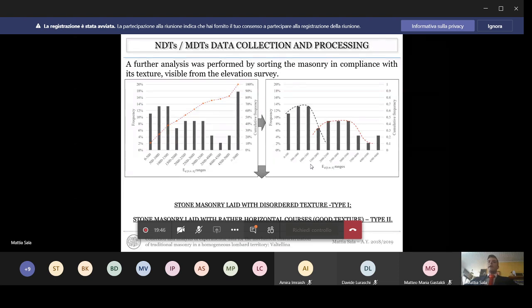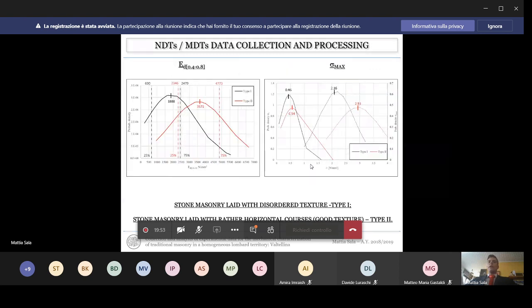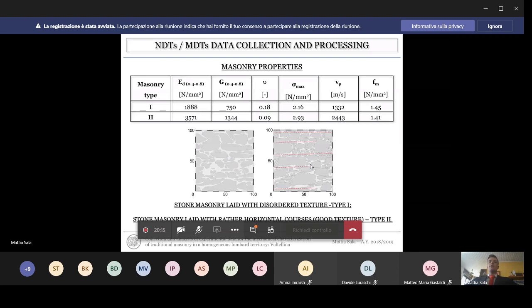By performing the mechanical analysis of the two typologies for what concerns deformability modules and compressive strength, the classification performed proved to be effective, as in both cases the mechanical properties of the masonry classified as type 2 are better than the one classified as type 1. Regarding instead the stress state, the two values are quite similar. So in the end, the mean mechanical properties of the two typologies are collected into a table, with 25 reference tests for type 1 and 15 reference tests for type 2.